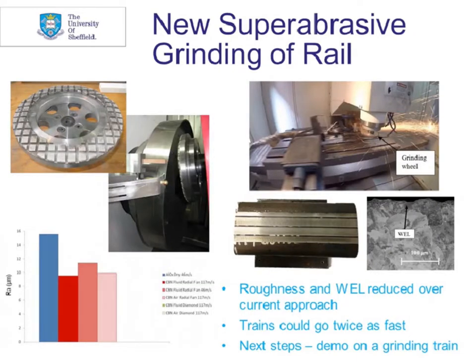As I mentioned, we're trialing some new grinding techniques with Network Rail. Initially, this was driven around the need to try and improve the speed of the grinding process, which at the moment is relatively slow, maybe running at sort of maximum of 10 miles an hour. So using super abrasives that are used extensively in the railway industry, we should be able to speed up that process. But actually, more importantly, as we've been looking at more recently, it should be able to give a much better surface quality to the rail in terms of both roughness, but also that phase transformation. So we should get very little or no white etching layer using this approach.